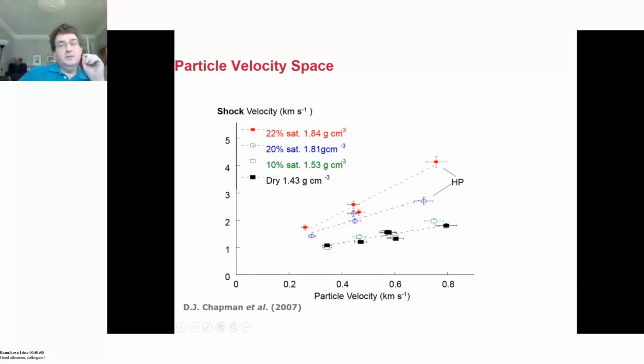But then if you added just a little bit extra water, so 22% saturation instead of 20%, you could have a quite marked difference in the shock response. So what this is indicating is that in the initial part, when you replace the voids with water, you have very little effect initially, but as you get towards filling the majority of the voids, very small variations at that point make a large difference in the shock response of the system.